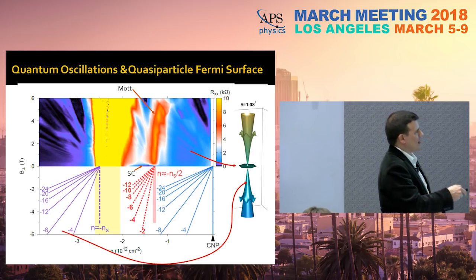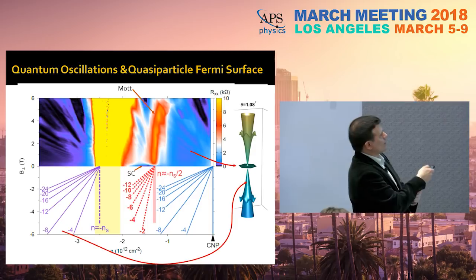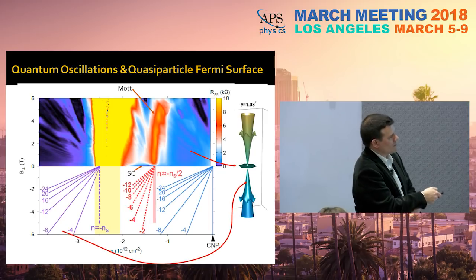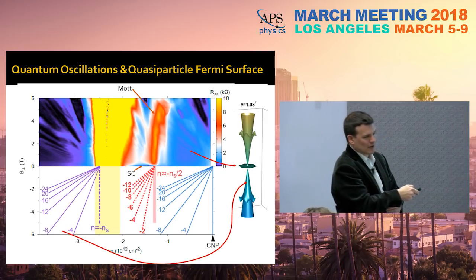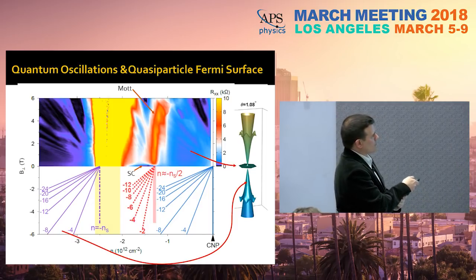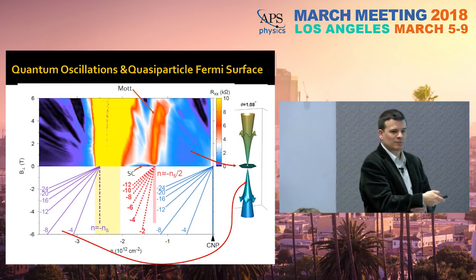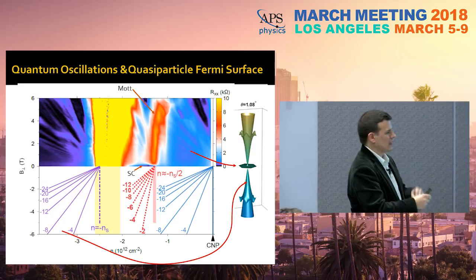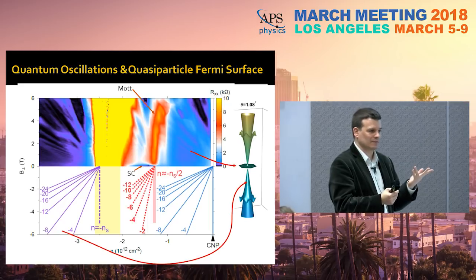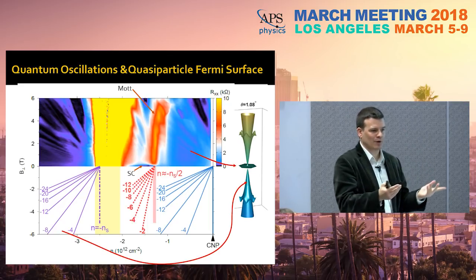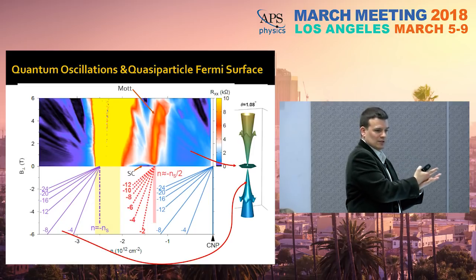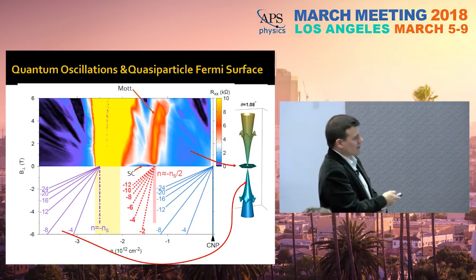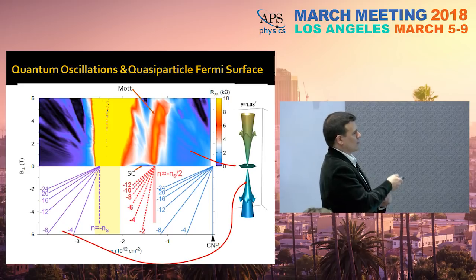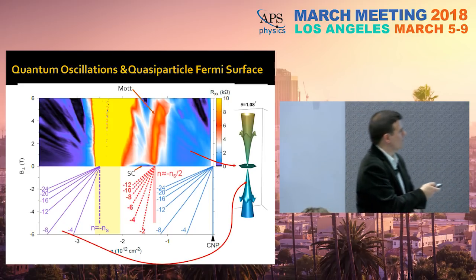Turns out that for these 2 fan diagrams, you can look at the evolution of your Shubnikov-de Haas oscillations in this density magnetic field plot, and you can look at the evolution of the maxima or the minima, and it gives you the degeneracy of your Landau levels, okay? So both for this and for this region, you have a degeneracy of 4, which is not very surprising. I forgot to say at the beginning, but I think most of you are familiar that electrons in graphene have this 4-fold degeneracy, spin and valley. Yeah? So you have spin up, spin down, valley K, K prime. This also goes and folds into this twisted band structure. So we were not very surprised that indeed these fan diagrams exhibit filling factor sequences of 8, 12, 16, 20, etc. We have seen this in all of the devices that we have measured, by the way.